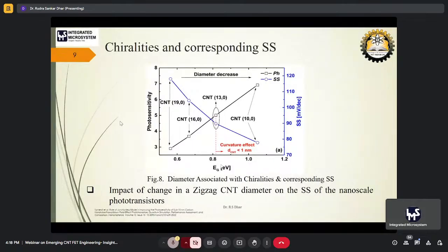So these are the corresponding structures that can develop. With 19.0 we are having the widest option, where we are seeing the variation of band gap with respect to photosensitivity and the subthreshold swing for different CNTs, I mean, for different N0 combinations of the CNTs. So the highest 19.0 is something like this, followed by 16.0. 13.0 is quite small, and then we have 10.0 over here, where in 10.0 the photosensitivity is quite high, whereas the subthreshold swing is quite low. So now it depends on what type of option we are looking into.